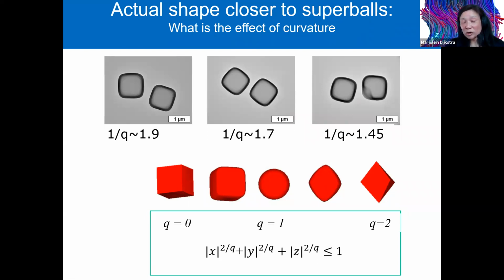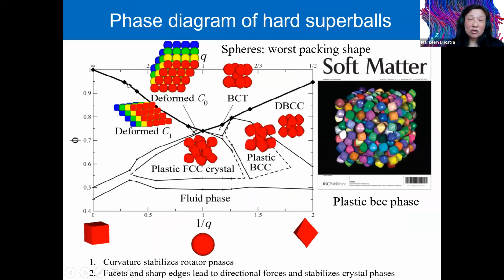We first use our crystal structure prediction method to find the densest packings. They are denoted here by this solid black line. And one can clearly see that the spheres are the worst packing shapes if we consider it with respect to the cubes and the octahedra. And this is well known in literature. So this is the phase diagram.